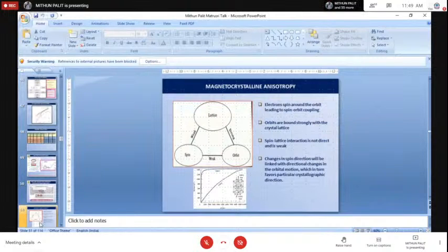So therefore, their moments are very much localized, and depending on the number of unpaired electrons available in the 4f shell, the magnetic moment is also very strong. And the other most important thing of this rare earth material is that the spin orbit coupling is very strong in this material. That means spin talks with the orbit very nicely, which is very weak in the regular transition materials such as iron, cobalt, nickel.